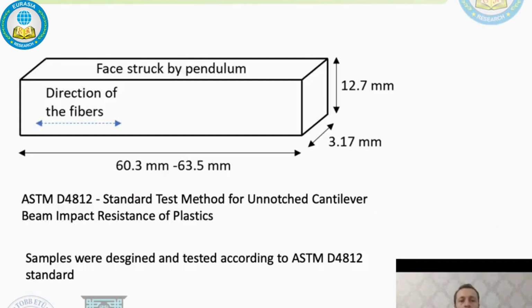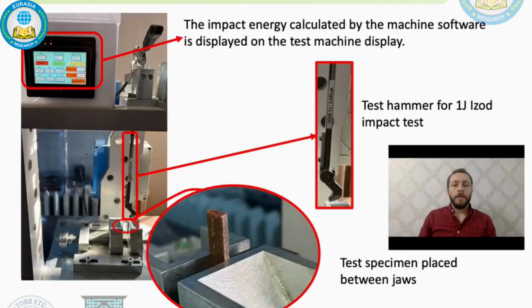Sample design and test setup. Samples were designed and tested according to the ASTM D4812 standard, which is the standard test method for unnotched cantilever beam impact resistance of plastics. In the standard, dimensions of the samples and orientation of the fibers are very important. These issues were given importance during sample design, and this is our test setup for impact test. Test specimens were placed and fixed between jaws as shown at the bottom of the figure.